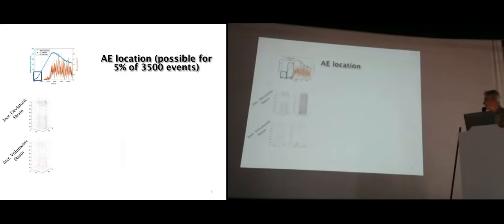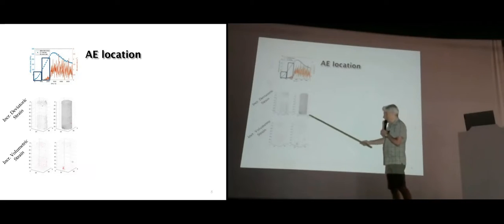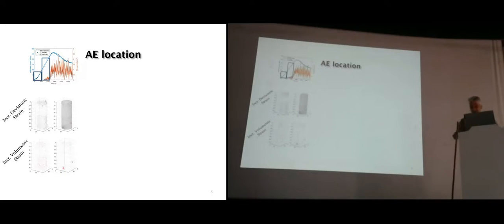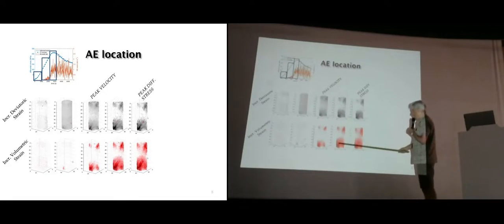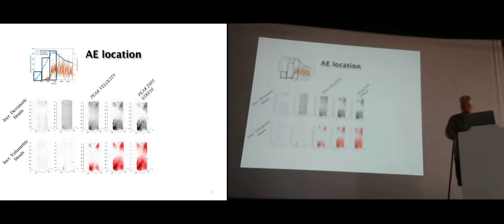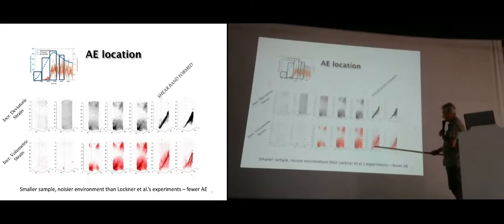And then this is what we see. This is maybe not that distinct. Here's an event. There are not many events. Here's an event in the sandstone. It doesn't produce as much as the granite. We see events that are on the fault plane, events that are off it. We see there's more than one attempt to localize the deformation. And sometimes acoustic emissions are associated with that. Sometimes they're just in the host medium. And then we can see some clustered along the incipient fault plane.